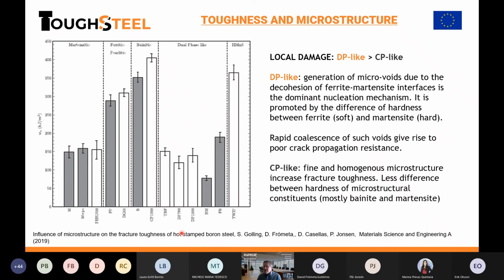So first, let's think about microstructure. If you remember the slides about microstructure, we have microstructures that are clearly dual phase, with a ferrite soft phase and a hard phase. These are what we call DP-like microstructures. In these microstructures, the voids accumulate in the soft area, generating decohesion of the ferrite-martensite interfaces. And in this DP-like microstructure, the toughness is low because once the cracks appear, there is no energy for the system to release, and the cracks grow mostly following the martensite islands that are brittle.